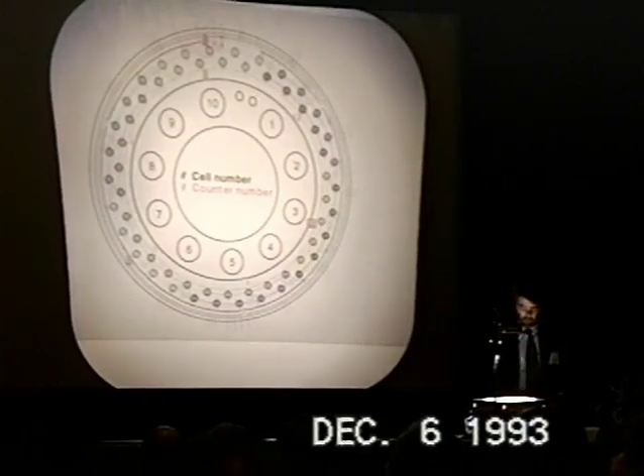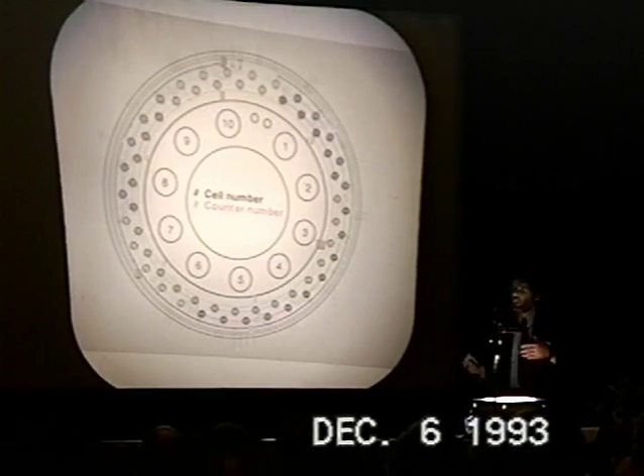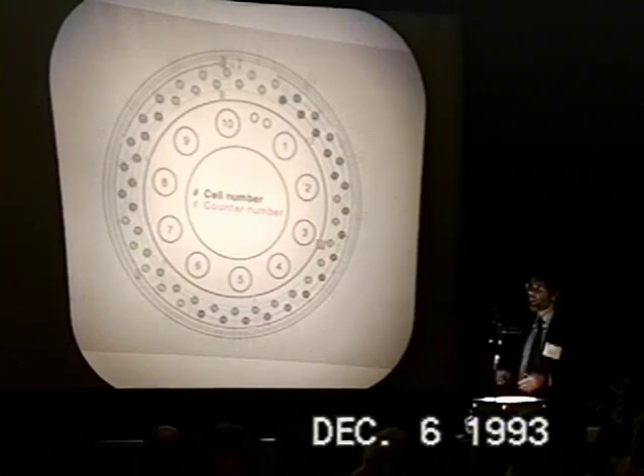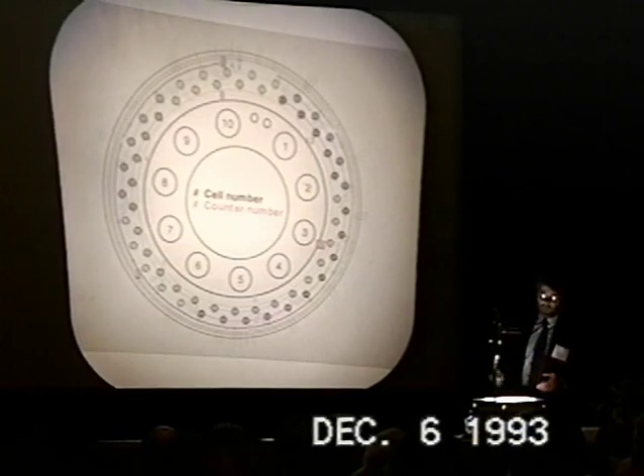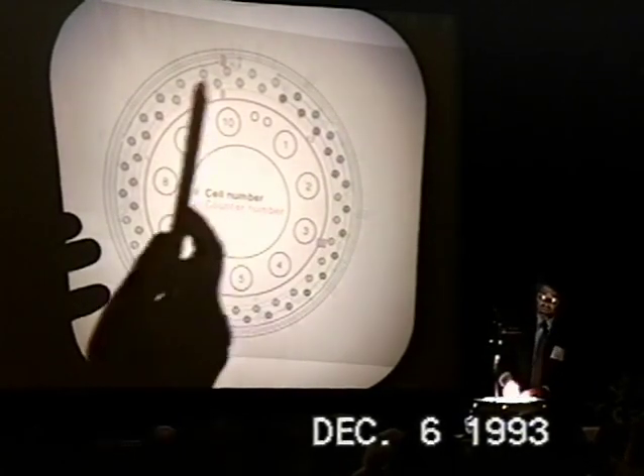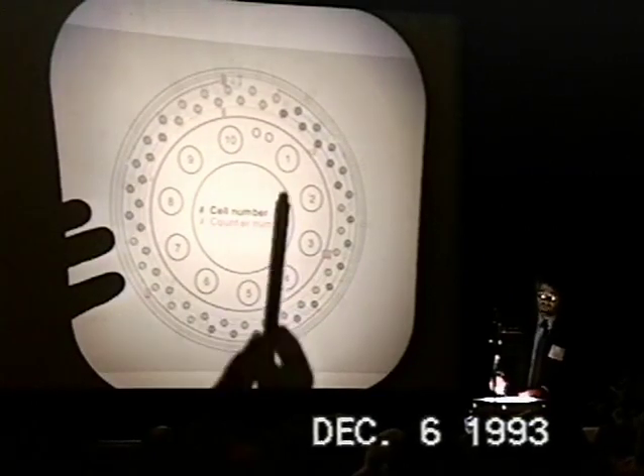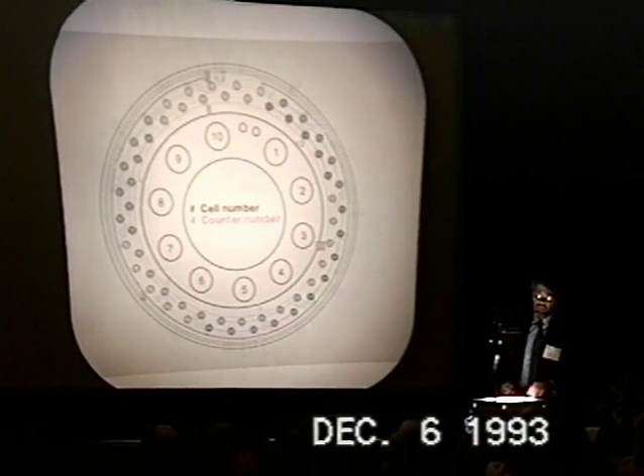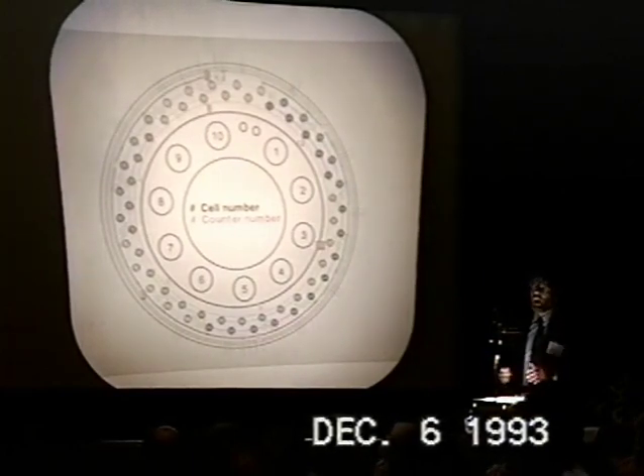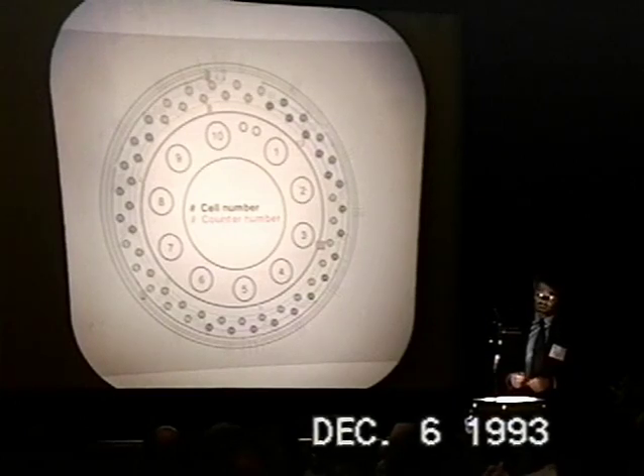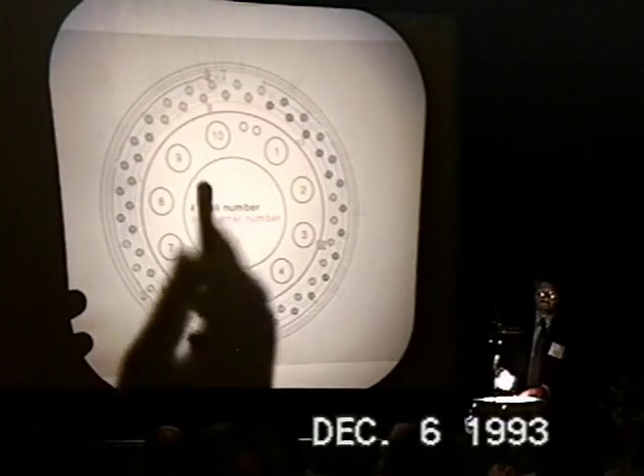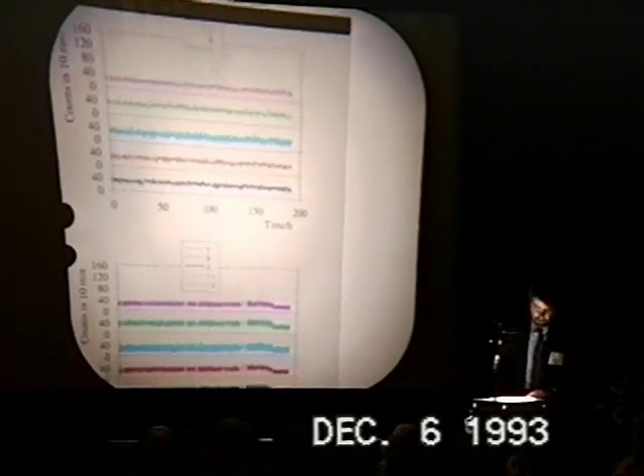Go to the neutrons. As I showed last year in Nagoya, we have a large neutron counter with 60 helium-3 tubes, which are divided in 12 groups, 12 separate counters, with separate electronics. In this detector, there are the tubes containing 10 cells. This allows us to have a certain degree of spatial resolution to have information on the source of neutrons. But we didn't find any significant excess of neutrons.